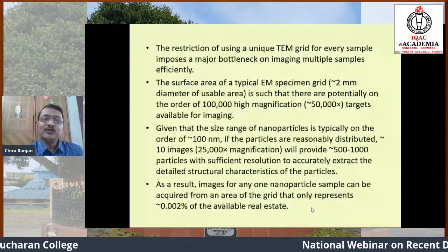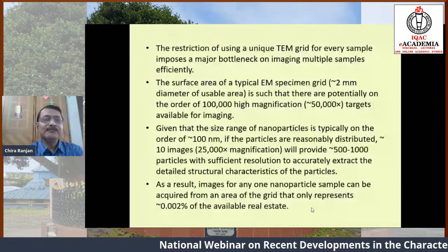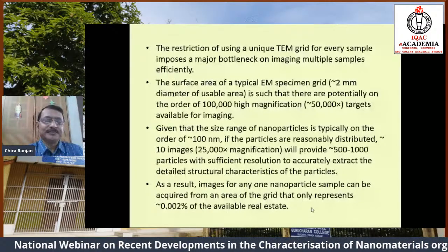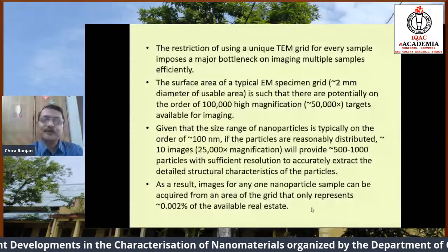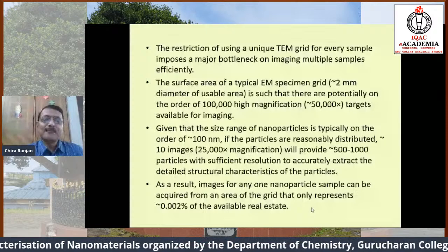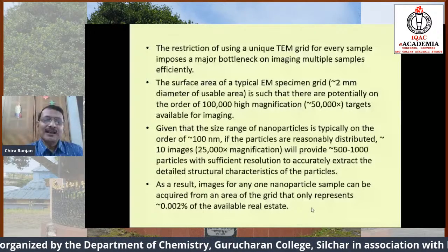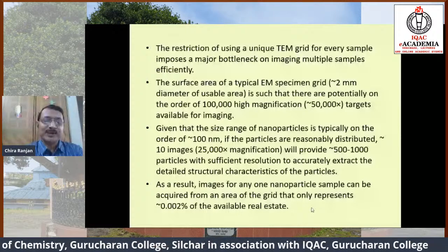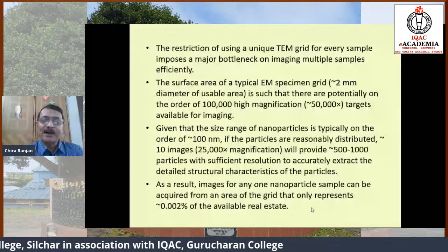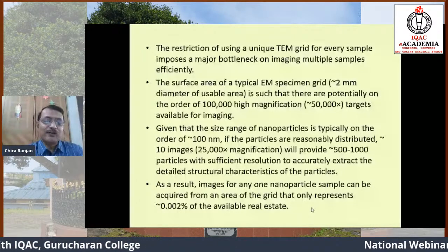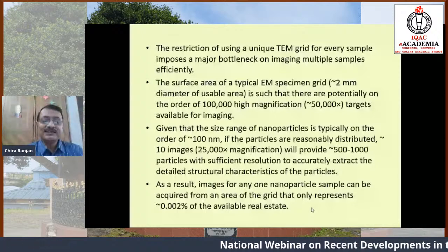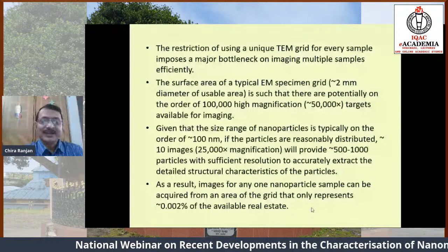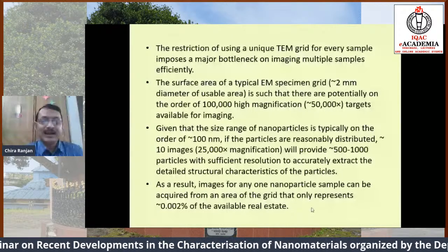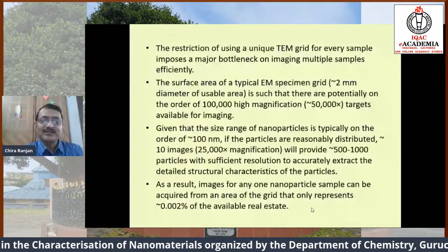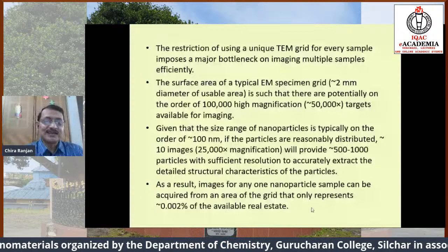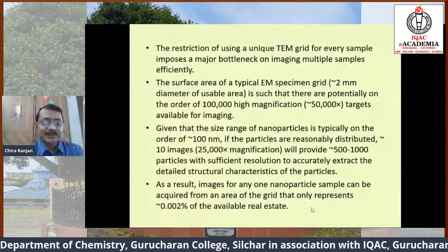The restriction of using a unique TEM grid for every sample imposes a major bottleneck on imaging. The surface area of a typical electron microscope specimen grid is such that there are potentially on the order of 1 lakh high magnification targets available for imaging. Given that the size range of a nanoparticle is typically of the order of 100 nanometers or so, and if the particles are reasonably distributed, to procure an image of about 500 to 1000 particles with sufficient resolution to accurately extract the detailed structural characteristics of the particle is a challenge.